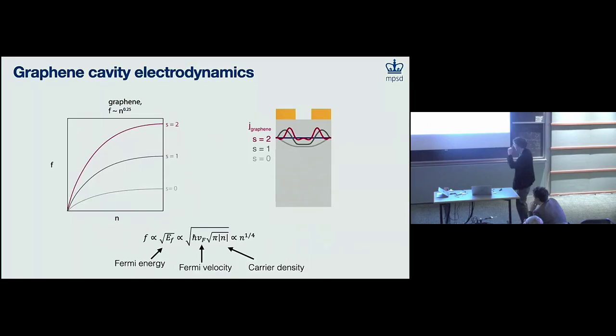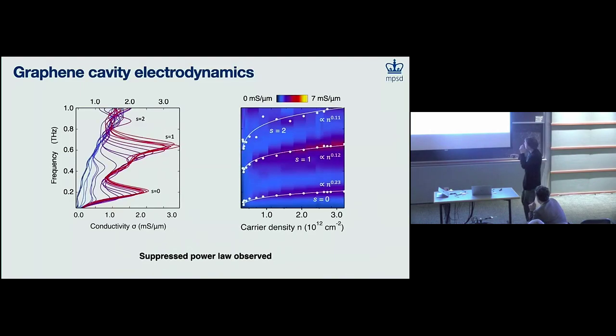Okay, so let's analyze this. So in general, it's very well known that in graphene plasmons, the frequency of plasmons should scale as carrier density to the 1/4 power, which you can just see from this relationship down here. It just has to do with the Dirac dispersion. And so if we had our monolayer graphene in this situation without any cavity coupling physics involved, this is what all of these modes that we see should scale as, n to the 1/4. So now you can see why I'm plotting the data sideways, because now we can compare the frequency versus carrier density, and now the color map here is the conductivity. So you can see that this lowest order resonance that we see does scale pretty close to n to the 1/4, as you would expect.